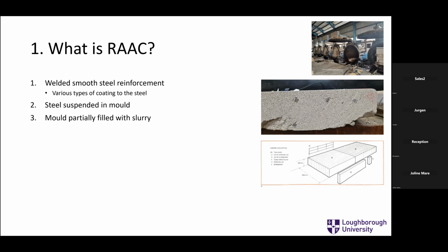So I mentioned the reinforcement, and it's welded, it's smooth, and it's got a coating on. Because some of you might be thinking, oh, aerated, that's not going to keep the water out. That's not good for durability. And you're totally right. The AAC bit is rubbish at durability. Water can go in, chlorides, carbonation, it carbonates really quickly. So for protecting the steel, it's terrible. Well, we know this, and so we put a coating on the steel.